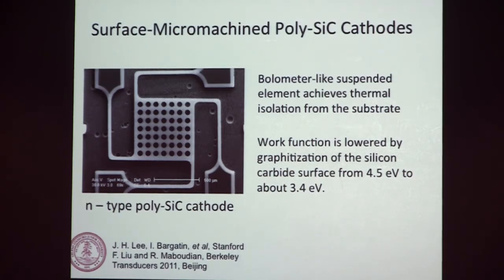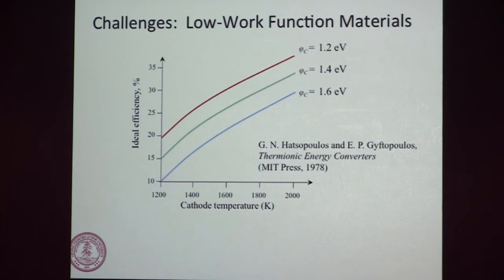So what's the thickness of the silicon carbide? The typical 1.8 micron, something like that, is a typical MEMS layer. Very much like polysilicon. So what we have done is very simple, like one mask surface micromachining. We use xenon difluoride, we use vapor HF, and things that are just to demonstrate the cathode. Where's the anode? We have an integrated package.